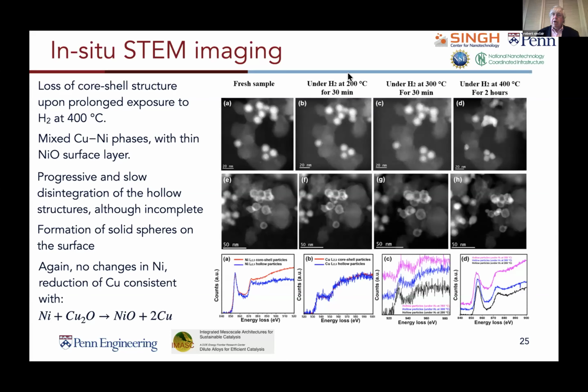What sort of currents are you using? What sort of doses? It depends upon whether we're doing the STEM imaging, the EELS, or the EDS. There's a variety of different configurations that we use. This was done in the aberration corrected NEOARM instrument, 200 kV. So there's some good dose that is needed to do the EDS and the EELS. We use spot size 6, sorry, in that. I'd have to go and remember the exact correlation with the current.